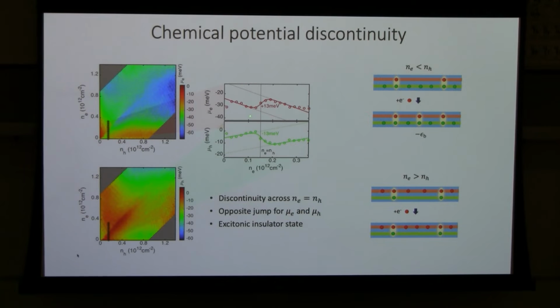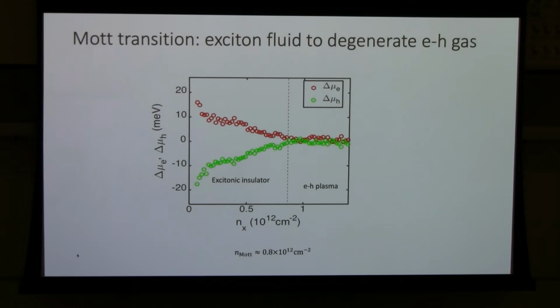We can use this as a way to determine the exciton binding energy and see how the exciton binding energy changes as a function of the exciton density. What we found is that the exciton binding energy actually decreases monotonically with exciton density, and it goes to almost 0 at a density of about 0.8 times 10 to the 12 per centimeter squared. This is what our theory calls a Mott transition between the exciton fluid and a degenerate electron-hole plasma. Okay, so these are the quasi-static behaviors of this exciton phase diagram.